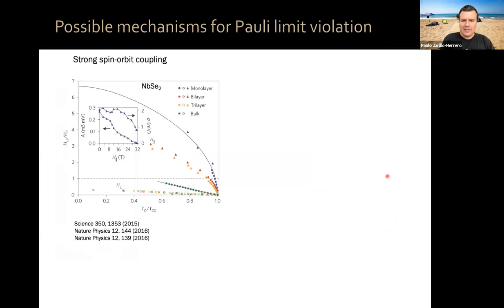there are a number of superconductors that violate the Pauli limit, and there are a number of mechanisms that allow violating it. For example, one that has been observed in a number of systems is systems which have very strong spin orbit coupling, such as niobium selenide, which is also a two-dimensional superconductor. In the monolayer case, Pauli limit violations of the order of 4 have been reported, with extrapolation of order 6 or so at low temperatures, okay?